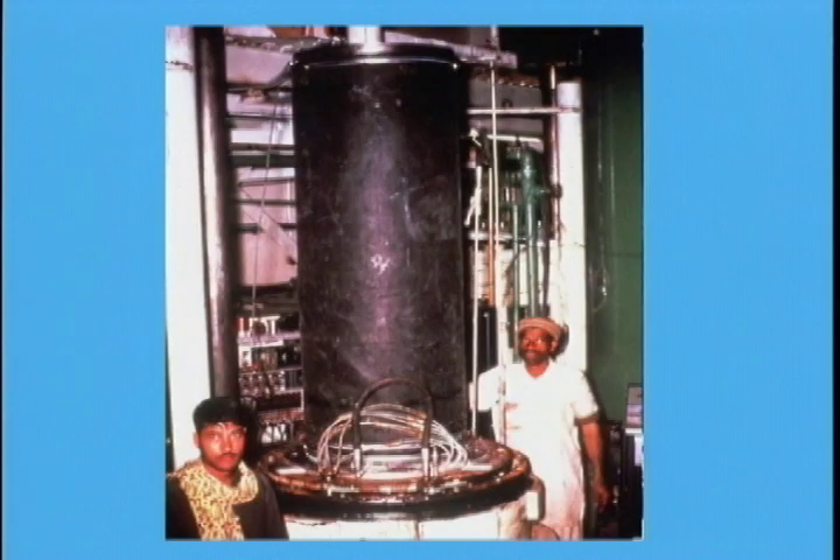To carry out stability analysis under any of the three rapid loading conditions, it is necessary to know the shear strength of the soil at all points along the failure surface. The preferred type of shear test is the triaxial test, where a cylindrical soil specimen is encased in a rubber membrane. A giant triaxial specimen 24 inches in diameter and 62 inches high was used for testing the impervious material at Tarbela Dam, which had widely graded material from 4-inch maximum size with 30% passing the No. 200 sieve.